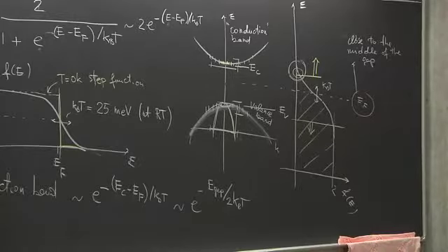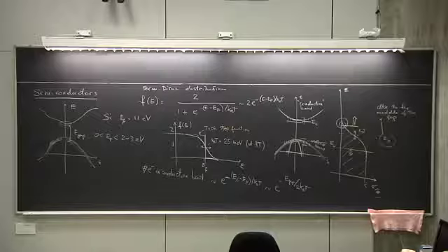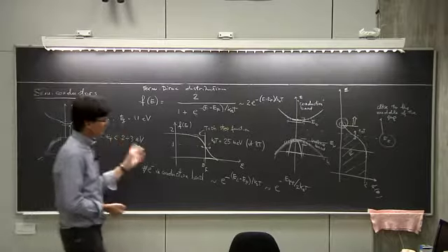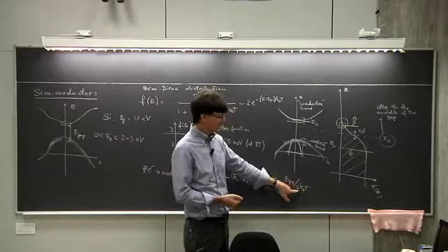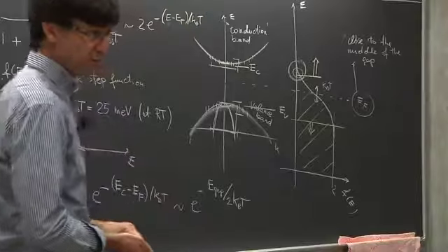So now it becomes clear why we classify systems. I mean, we use this terminology, semiconductors, to classify systems with an energy gap between 0 and 2-3 electron volts. Because if this is 25 milli-electron volts, twice kBT is 50 milli-electron volts.